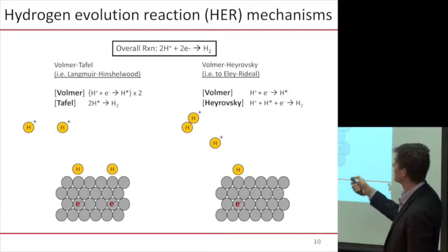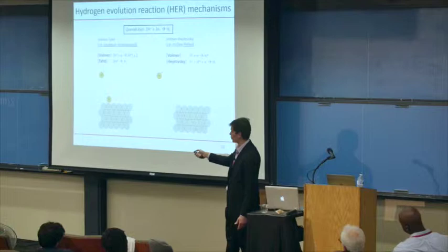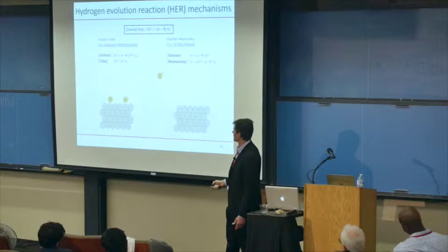The Volmer-Tafel mechanism starts with a proton in solution landing on the surface, making an adsorbed hydrogen atom. The second proton comes down on a different site. Now you've got two of these H's. They come together, form a molecular bond, and take off. Voila, you've made your H2.